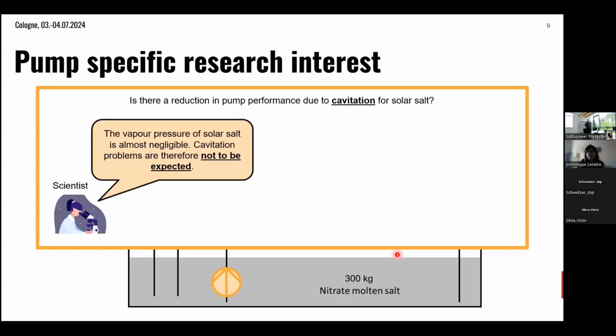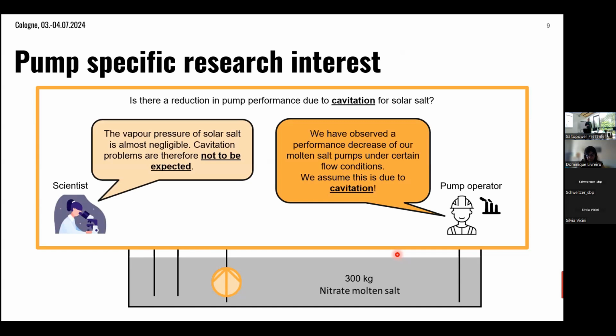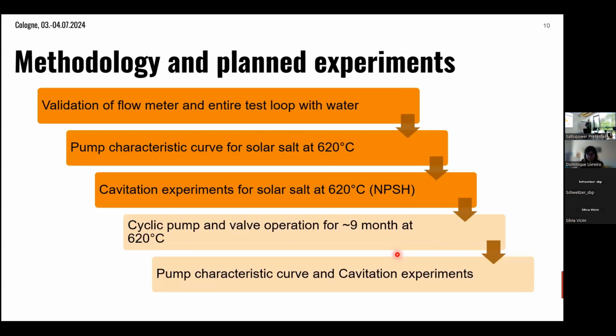And from the scientist's point of view, we might say, okay, the vapor pressure of the molten salt is actually quite low, so we would not expect much of a problem with cavitation. But we also hear from pump operators that they experience a drop in performance when they reduce the pressure under certain flow conditions, and they assume that this is due to cavitation. So to answer this question, we did some tests.